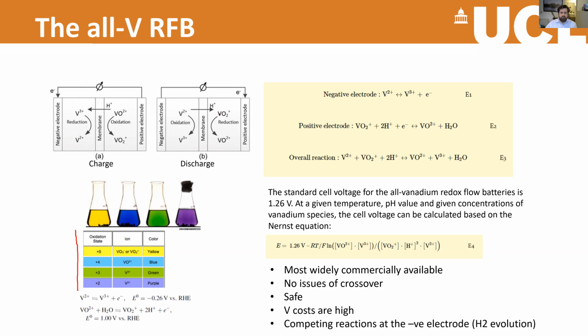And so in the positive electrode, when we're discharging the battery, we're going from vanadium 5 to vanadium 4. And in the negative electrode, when we're discharging it, we're going from vanadium 2 to vanadium 3. So you can think of the charge state as being vanadium 5 and vanadium 2, giving this sort of cell potential of about 1.2 volts. And then we're discharging to vanadium 4 and vanadium 3, which is the sort of lower energy state from which we can then recharge the battery back up to fully charged.